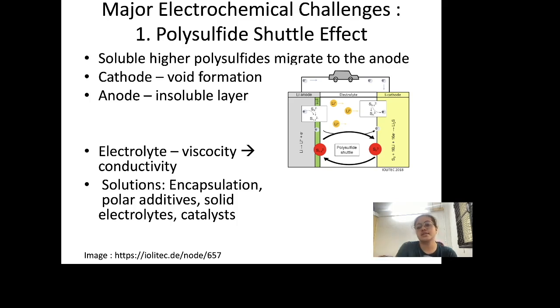Secondly, when you come to the anode side, as a result of this cathode effect, these lower sulfides, like lithium sulfide, when they are not going over to the cathode side, get precipitated onto the lithium anode, and these have lower conductivity, which is something I will get to later on, how that specifically affects the cathode. But they have lower conductivity, and they are also insoluble. So they essentially form this low conductivity and insoluble layer on top of the anode, which reduces the reactive area of the anode and the reactivity of the anode, and essentially a lot of loss of performance of the anode.